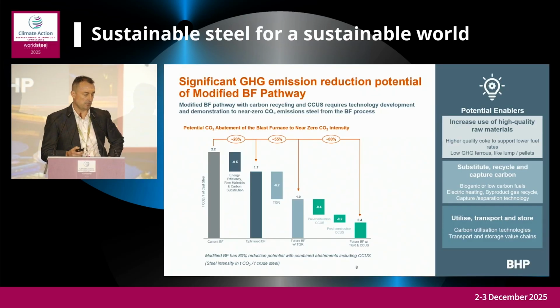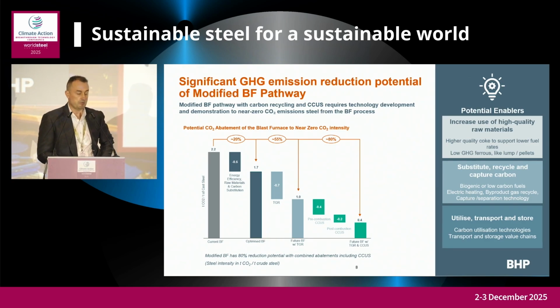For the blast furnace, I think this is now becoming a common understanding that the blast furnace pathway to that near zero intensity has the combination of technologies which include increasing energy efficiency, raw material blends, which includes higher quality coke, the greater use of lump and potentially pellets over sinter, to really step down that emissions by 10 to 20%. Then you have the recycling or carbon loop effect of the top gas recycle back into the blast furnace to step down even further to about 50% reduction. But to really get down to that near zero intensity, you need the carbon capture and utilisation and storage.